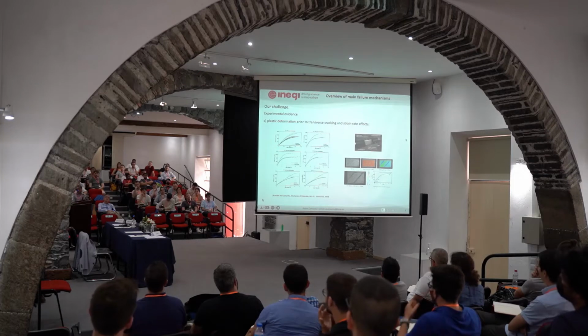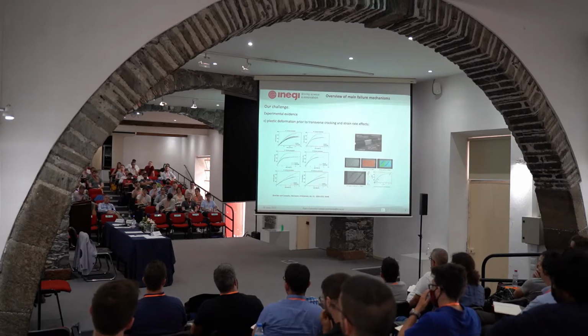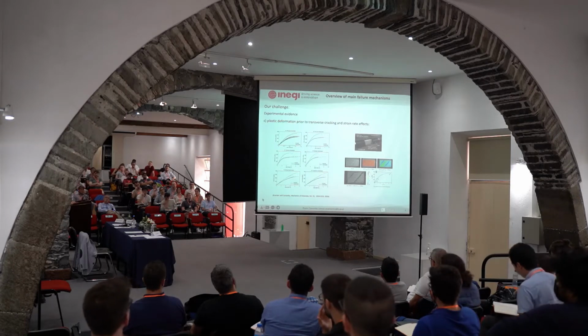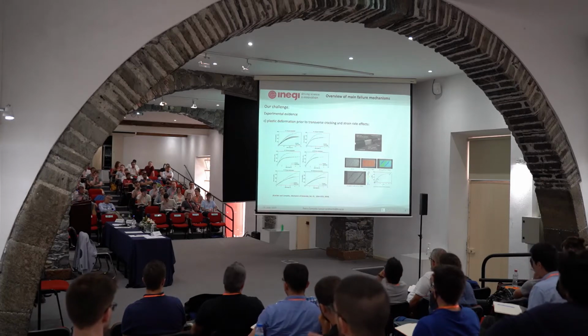Now, we realized that often, the Hopkinson bar setup was being used as it was for metals, right? People press the button, get some curves, and we realized that the results were completely wrong in some cases. So we needed to do a lot of work in terms of shaping the pulses, and we now obtain, I think, reliable information on the response at high strain rates. Okay, so this is something that we need to take into account as well.